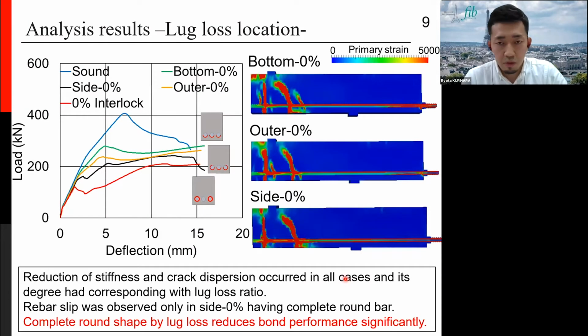First, let me introduce the effect of lug loss location. Basically, all cases show stiffness reduction and a crack concentration trend, and the degree of reduction corresponds to the lug loss ratio. The load dropping by rebar slip was observed only in the 0% case, which has two complete round parts. So it can be said that complete lug loss reduces the bond performance significantly, but rebar slip can be prevented if sound interlock remains in a part of the rebar surface in each rebar.